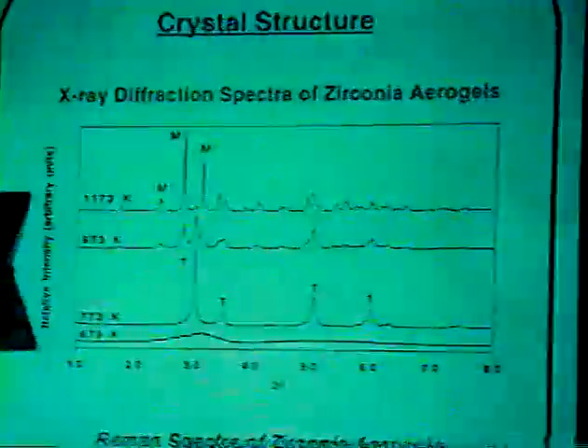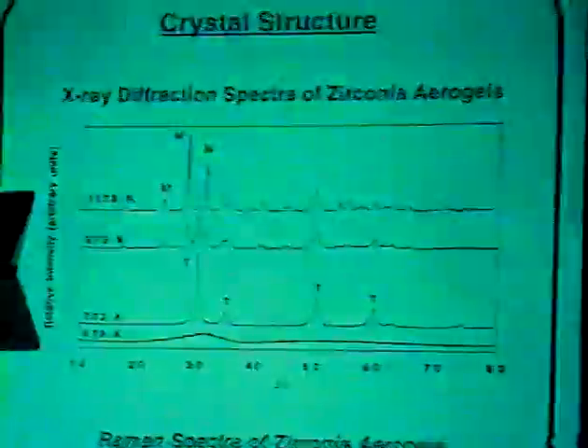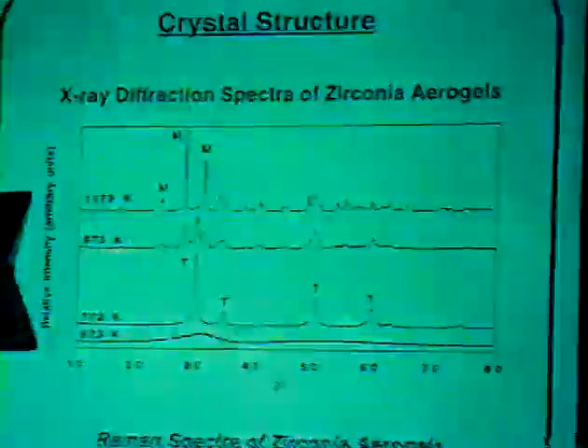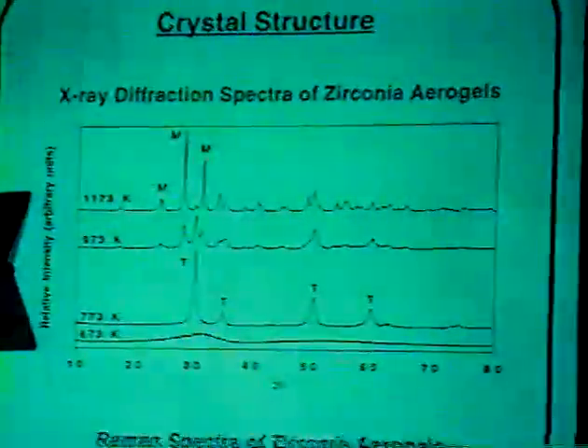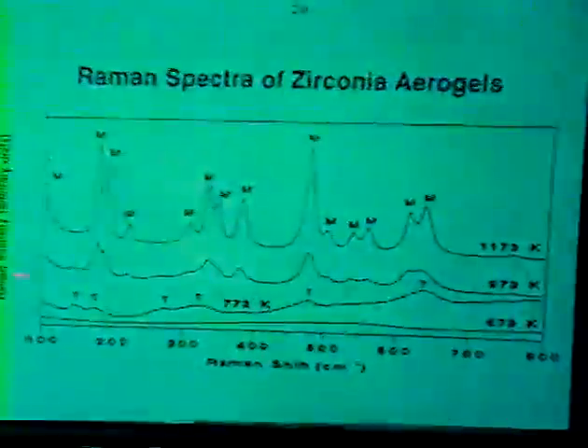When we look at the structure of our zirconia aerogels as a function of heat treatment, this is what we found. Let's first focus our attention on the upper panel, which represents X-ray diffraction patterns of the zirconia aerogels synthesized at an optimum ratio in order to maximize the surface area. And then we look at the X-ray diffraction result as a function of heat treatment. Notice that even after heat treatment at 673 K, the sample remained X-ray amorphous. At 773 K, the sample did crystallize, but it crystallized into the tetragonal form. I would like to remind you that the phase diagram suggests that bulk zirconia is stable in the monoclinic form at that temperature. Upon successive heating, the material did crystallize into the monoclinic form as indicated by the letter M in the X-ray diffraction pattern.